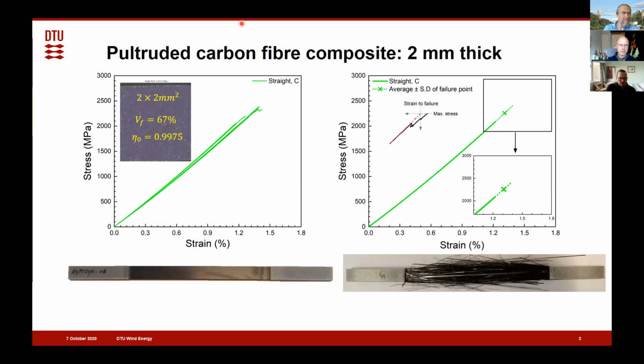But we have done a similar study for the pultruded carbon fiber composite. For that, we cannot vary the thickness because that's given by the pultrusion profile or the pultrusion process. So here we have a 2 millimeter thick sample again, or even more. Here we have a case where we have rather uniform distribution of fibers, very aligned fibers. So here's this fiber orientation efficiency factor, which we can calculate. That's a reduction corresponding to the misalignment of fibers, which is very small here. And we also, for this, have even a higher fiber volume fraction.